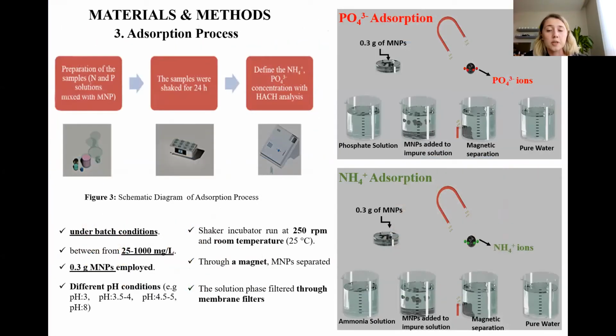Well, the adsorption experiments were also conducted under batch conditions, and each one performed separately, I mean consecutively, maybe we can say. It's actually out of the simultaneous experiment. And the steps of the adsorption process are as seen on the side. These experiments were carried out under batch conditions. The required amount of the magnetic nanoparticles was 0.3 g, and during this study, different pH conditions were performed.